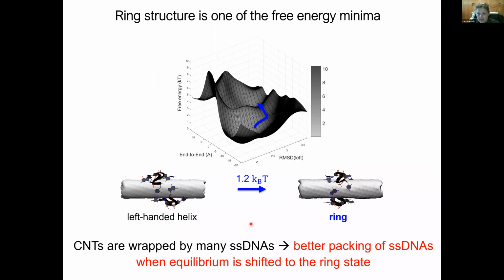If we plotted the contour plot like a 3D surface, we could also check what is the barrier for the system to go from helix to ring. It turns out to be only a kT of energy, which means it takes only thermal energy for the molecule to transition from helix to ring conformations. That means this transition from helix to ring could be happening in an experimental system all the time. So we observe the rings, and they are definitely free energy minimum states.